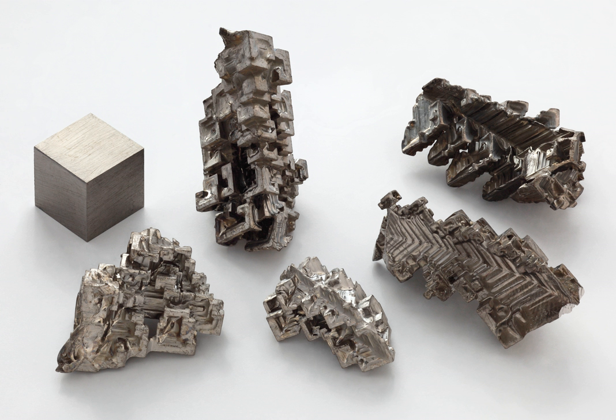Bismuth is used to make free-machining steels and free-machining aluminium alloys for precision machining properties. It has a similar effect to lead and improves the chip breaking during machining. The shrinking on solidification in lead and the expansion of bismuth compensate each other, and therefore lead and bismuth are often used in similar quantities.